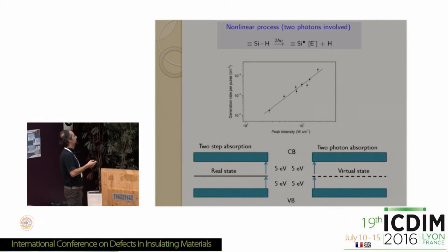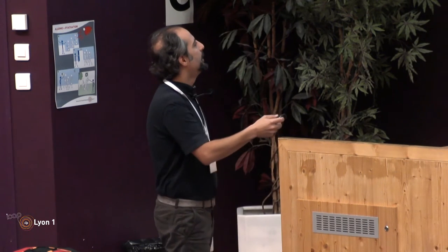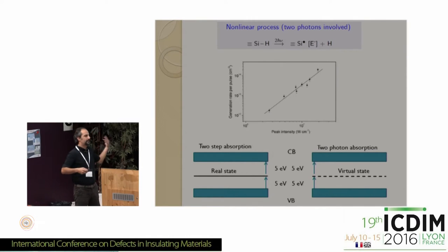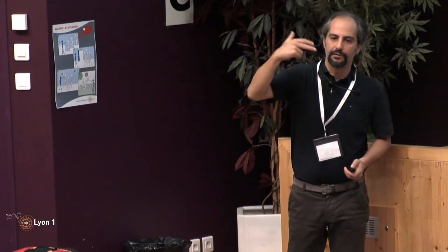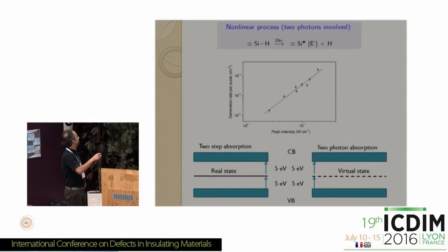However, there are, in general, two possible scenarios which are consistent with this kind of result. One is so-called two-photon absorption, which is the coherent and simultaneous absorption of two photons from the electromagnetic field, and doesn't need a state in between. You only need what a theoretician would call a virtual state. The other possibility is so-called two-step absorption, which is the consecutive absorption of two photons. First absorption brings you to a real state, which has a certain lifetime, and during this lifetime, you absorb a second photon, and from there, you jump to the conduction band. Now, this is much more efficient than this. So two-step absorption, if you have a real state in between, is much more efficient than two-photon absorption.